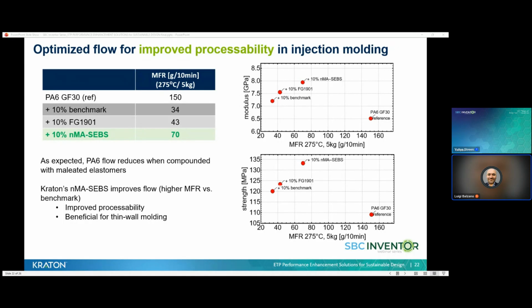When we look at the processability in terms of flow characteristics or rheology more broadly, it is well known that modification with the maleated elastomers leads to a reduction of the flow, degradation of the rheology in general. And this can be sometimes also severe. In this study, we observed that while all maleic anhydride modifiers lower MFR compared with the polyamide 6 GF30 reference, the novel maleated SEBS mitigates the deterioration of the rheological characteristics and demonstrates an optimized MFR for injection molding between these samples. This is very important, especially in applications that require injection molding at thin wall levels.